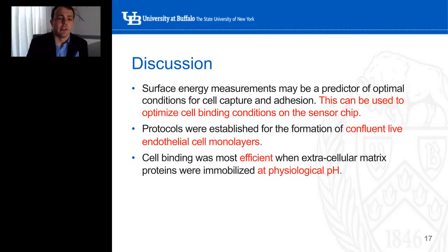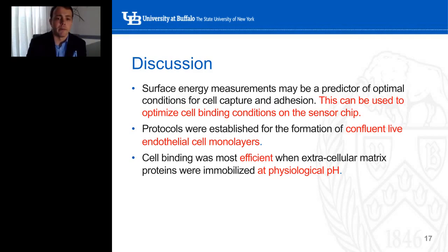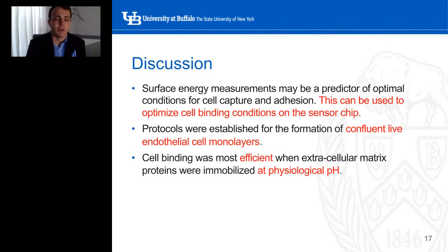Therefore, we used surface energy measurements of protein films to predict the optimal conditions for formation of a confluent live endothelial cell monolayer. In particular, more polar proteins with higher Lewis acid character form monolayers more efficiently. Monolayer formation will be important in SPR studies where specific drugs or hyperosmolar or hypoosmolar conditions are used to test cell responses. We also found that cell binding was most efficient when extracellular matrix proteins were immobilized at around pH 7. Studies where we tried to optimize EDC-NHS amine coupling using proteins in a reduced pH solution showed very few cells adhering, likely due to unphysiological denaturation of proteins at lower pH.